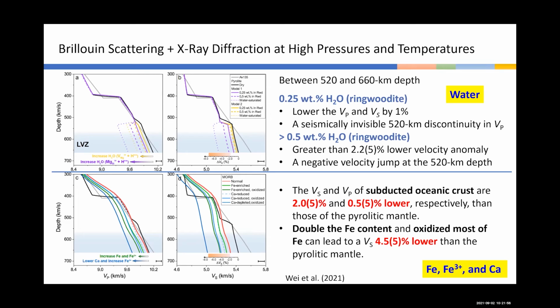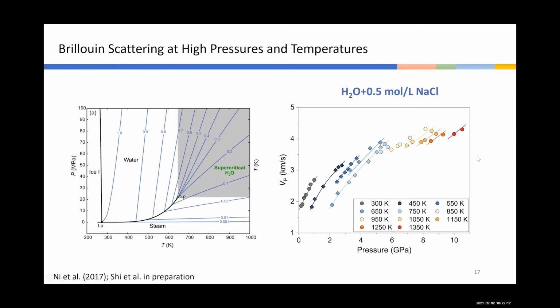So this is another example where we use the experimental results obtained from Brillouin scattering at the GSECARS. We try to understand the formation mechanism of the low velocity layer at the bottom of the transition zone. So this is about the mineral. Actually, we can also use this technique to get the sound velocity of fluids. Here I show you one example from our most recent work, which is unpublished: we measure the sound velocity of water fluid, water plus 0.5 mol/L sodium chloride.